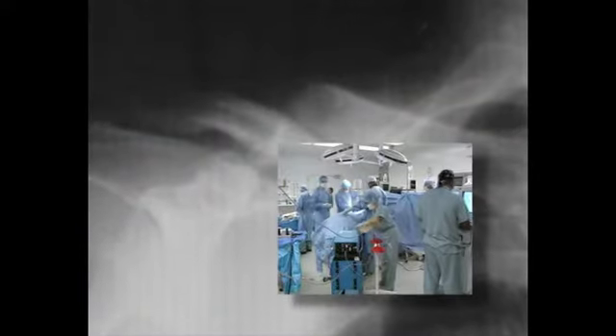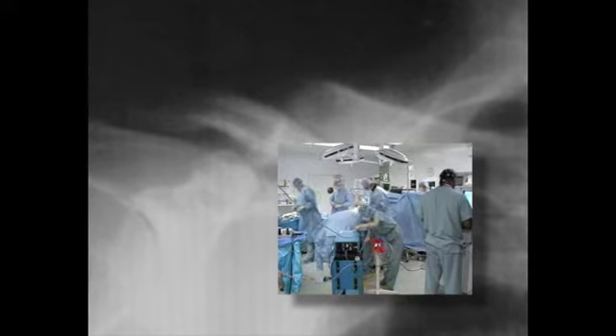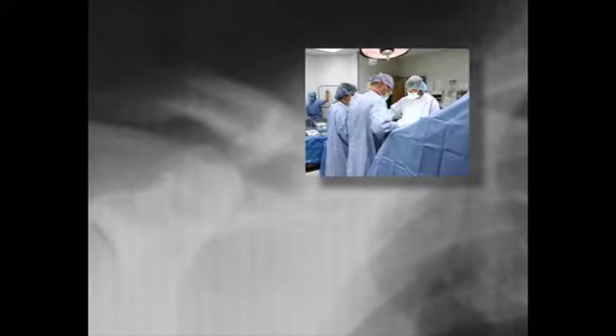Surgical examination confirmed that the patient had a fibrous union through the fracture site. In addition, a butterfly fragment from the original injury was grossly displaced, but connected to the fracture site by fibrous tissue. The fracture site was approached through a small exposure, and the fibrous tissue was debrided from the medial fragment. Next, the medial fracture end was clearly exposed and brought up through the surgical site. The medial canal was pre-drilled to allow clavicle pin insertion.